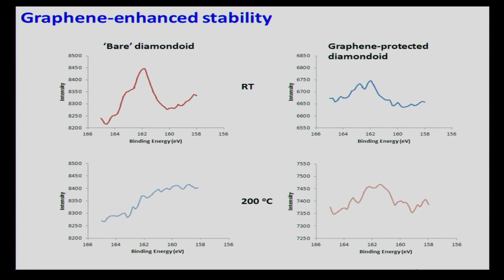And it's not only stable to radiation, it's also stable to temperature. This is also important because for actual use of these electron sources, you need to bake them from time to time to get rid of the contaminants. When you do that, you need to heat up the electron source to about 200 degrees. This is simply not possible if you only have a monolayer of diamondoid on this gold surface. They would just be boiled away into vacuum. But with the graphene coating, we're again confining the diamondoid species on the surface, and it prevents the dissociation of the diamondoid species from the surface.